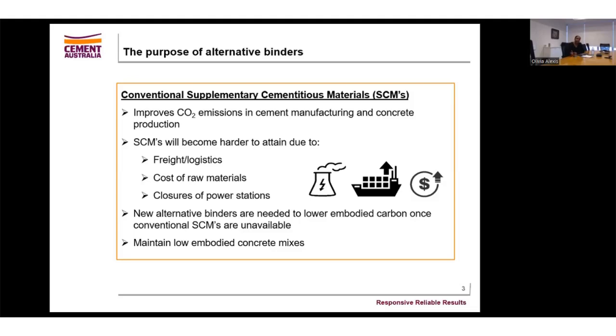That said, we're not always going to have fly ash and we're not always going to have slag. If we take slag, for instance, when we look at the freight and the complexities of logistics, or maybe even the increase in material costs, we have to understand that even now it's becoming quite scarce for us to attain some slag material and import it into Australia. We're going to get to a point where we're not going to be able to use slag in our mixes because of these limitations. Or if we look at fly ash, the closure of power stations, say Eraring moving their closure date to the next 5 years, we won't always have the virgin fly ash that we currently use in concrete to reduce our carbon emissions. So we'll need substitutes. And so that's when alternative binders will come about in order to maintain low carbon concrete mixes.